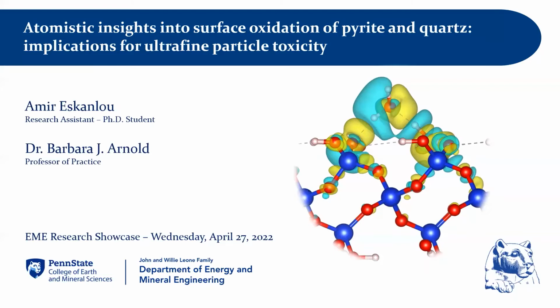And then on the surface of pyrite, the adsorption of oxygen is more thermodynamically favorable than water, which means that surface alteration of pyrite in the atmosphere is more dominantly done by oxygen than water molecules. So pyrite surface oxidation is due mainly to the presence of oxygen molecules. Such interactions lead to the formation of Fe2+ OH2, Fe3+ O2-, Fe3+ OH-, Fe3+ OOH-, and oxygen-sulfur interaction, and then the formation of hydroxyl radicals.